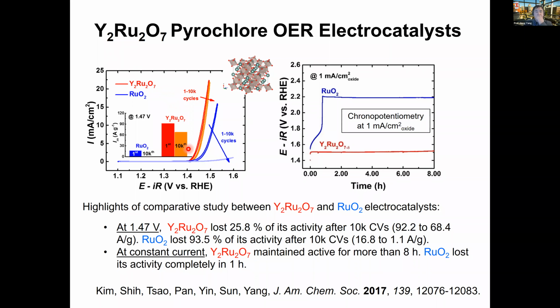So here's what we observe in this particular system. This is using ruthenium oxide as a reference catalyst. If you compare the yttrium ruthenium oxide pyrochlore structure, doing the simple CV test in comparison with the ruthenium oxide system, you can see that if you do 1 to 10,000 cycles, the pyrochlore-based system is very stable, but the ruthenium oxide is down. So there has to be something that the yttrium does to the system. Okay, so this is our first system, and also the thought process goes into the design of using the A side to control the B side properties.